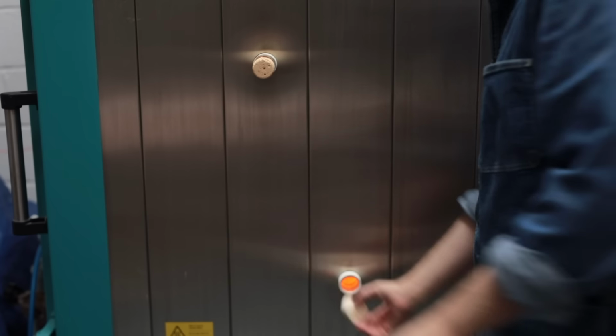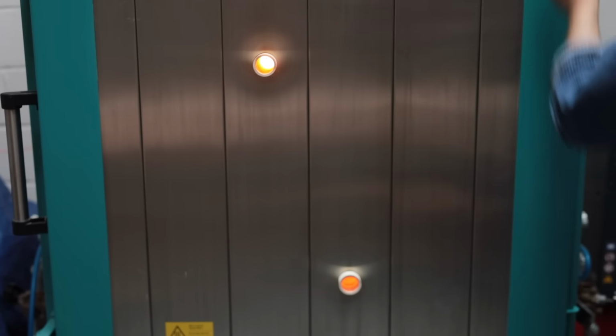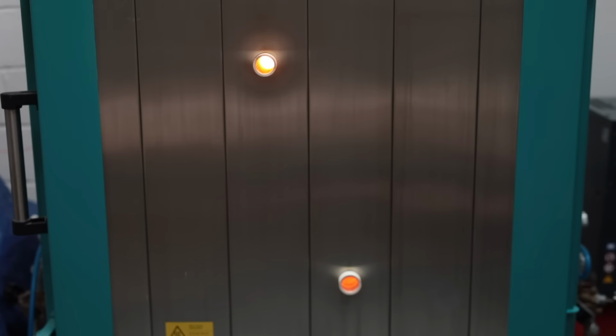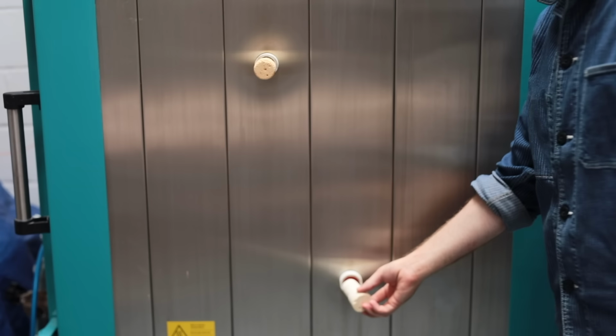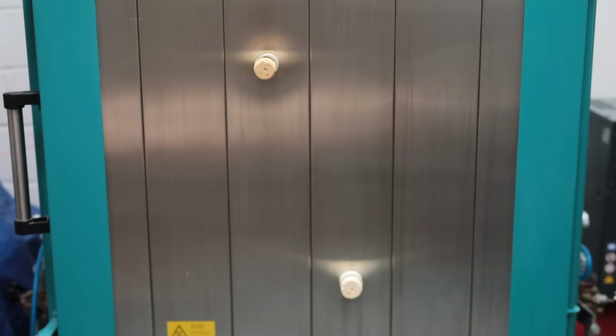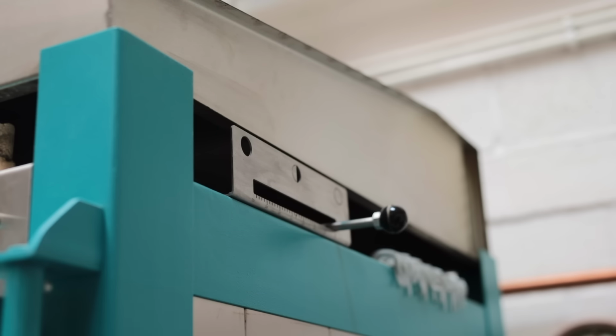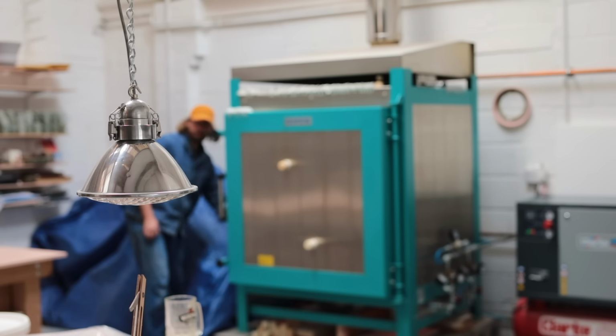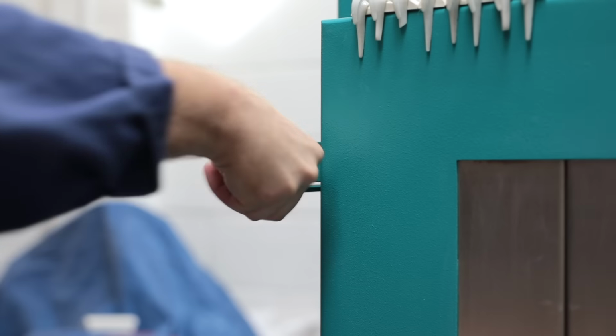The last thing I do is take the bungs out of the spy holes and I fully open the damper, and from this point I let it crash cool back down to 1000 degrees Celsius. This helps to retain colour and gloss. It's then fully closed up and allowed to cool down slowly for a couple of days.